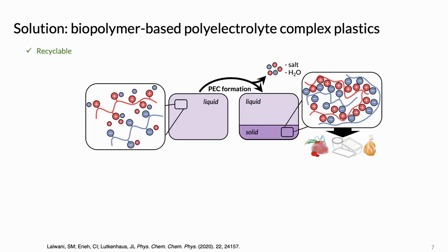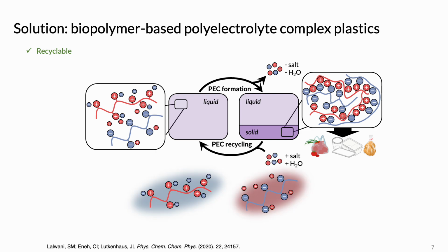That solid material can be formed into a bag or a container, and after its use, thermodynamics dictates that by adding an excess amount of salt or ions and water, we can reverse the solid formation where the salts actually screen the charges on the polyelectrolytes, thus making them neutral and not so ionically attractive to each other. And this brings a material from a solid in a liquid solution to a pure liquid. And we can repeat this cycle for full recyclability of the solid material without changing the length of the polymer chains.